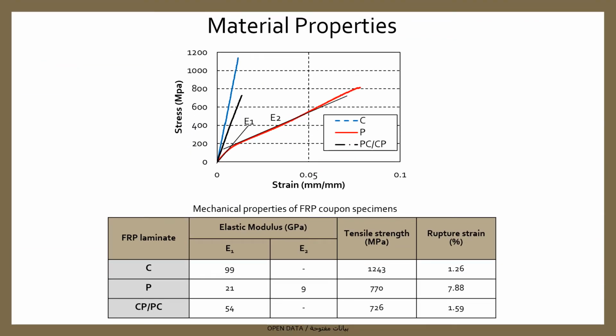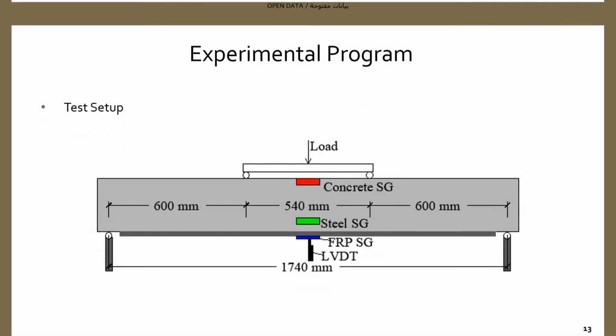As shown in this graph, C samples had a linear elastic response and P samples had a bilinear stress-strain relationship with two moduli. On the other hand, hybrid FRP composites behaved in a linear elastic manner before failing at a low rupture strain, which is slightly higher than that of the CFRP sheet. This shows that the failure of the hybrid mix was dominated by the failure of the CFRP sheets.